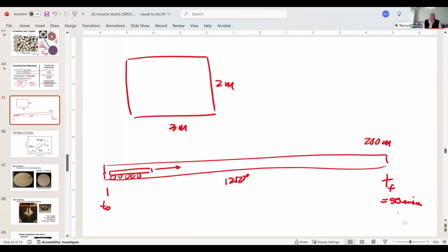The front end of this tile is going to be hot before the back end sees heat. When I sinter this piece, this thing is going to do this, and then it's going to do this, and this part will densify and shrink. My shrinkage is about 16 to 20%.